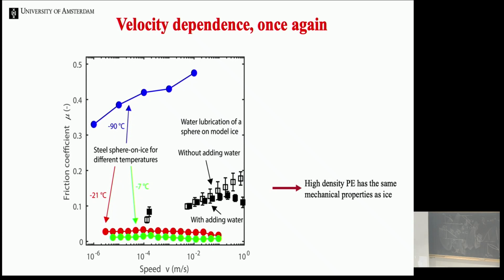But I showed you yesterday the friction on high-density polyethylene because it has very similar mechanical properties to ice, and you see that even if you add water there, the friction of the skate on ice is actually much, much lower. Yeah, so this is really an exceptionally low friction system. And so the question now is, what happens?